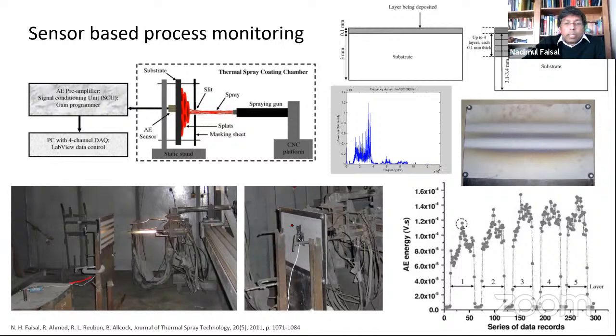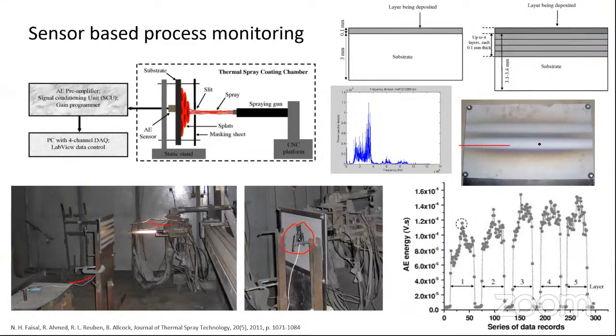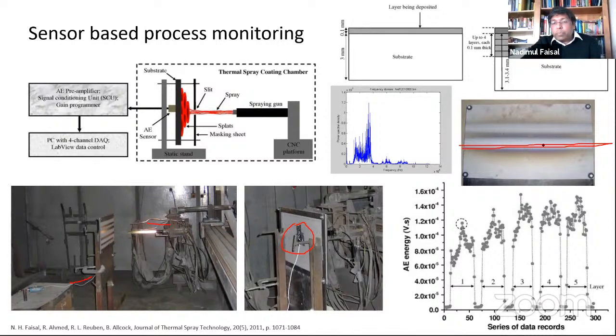Here you can see the sensor behind the substrate, and you can spray on the plate. You can see here we have sprayed a number of layers. It was thermal spraying. We did about 1 millimeter thick, and for each layer we build up, you can see the energy of acoustic emission going up and up. Each of these data points is actually an average of hundreds of data files. However, if you analyze each of those files, you can see that it will have many additional signal features coming either from micro cracks or layer by layer cracks, which could happen. So this is one of the experiences we have.